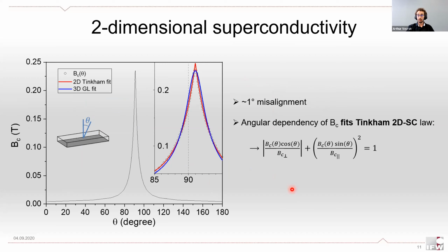Now, since we have a very thin structure with a thickness very close to the superconducting coherence length in bulk samples, we would like to investigate the dimensionality of the superconductivity in this sample. So for this, we look at the behavior of the critical field versus tilting angle of the field. Once again, 0 degrees is for a perpendicular field, 90 degrees for a planar field. And so we expect to have a maximum of critical field for 90 degrees, for the planar field. What we find out actually is that we have a maximum at 91 degrees.